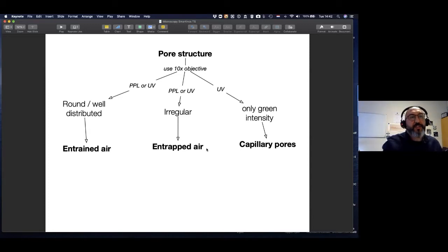And in order to examine the pore structures, we typically use ultraviolet light, so very low wavelength light. The main reason is, if you remember, when we prepared our samples, we used a special dye, special color pigment in our epoxy. When we impregnate, it hardened my concrete, it made it really strong, but also it gave a new property, and that is all the pores and cracks are now filled in with my epoxy with a special color. And that color I can observe by shining ultraviolet light, and then it will release a special green color, which I can observe and take pictures of and even do image analysis to quantify the amount.